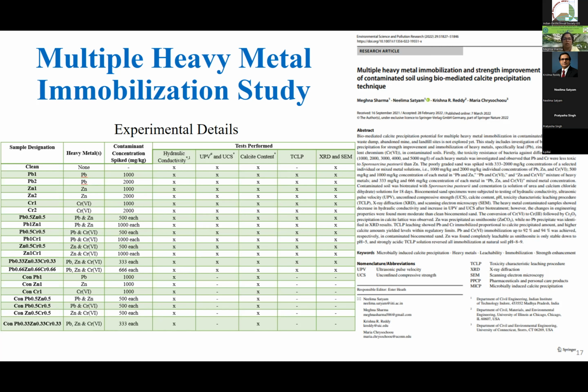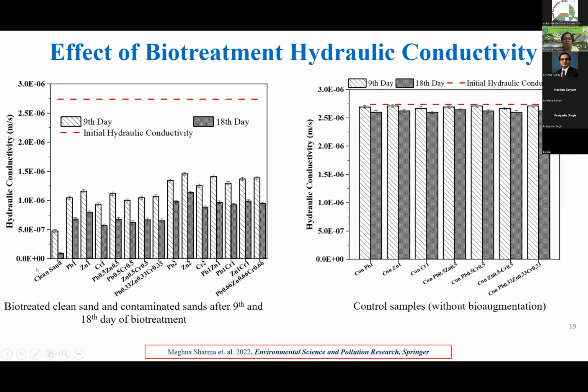In the clean sand, where no contamination was provided, the hydraulic conductivity reduction was higher. The maximum reduction in hydraulic conductivity, either on the 9th day or on the 18th day, was higher compared to the contaminated soil. It means that the contamination is still affecting bacterial growth. Now coming to the results of contaminated soil with lead, zinc, and chromium. Zinc was found more toxic compared to chromium and lead.